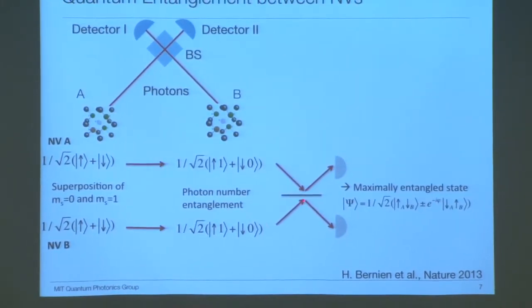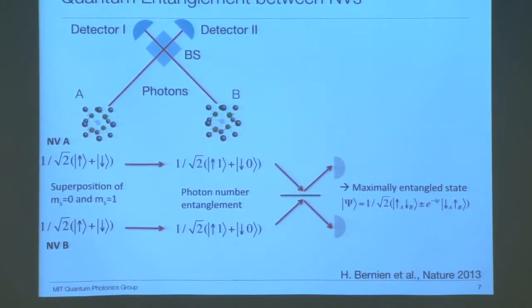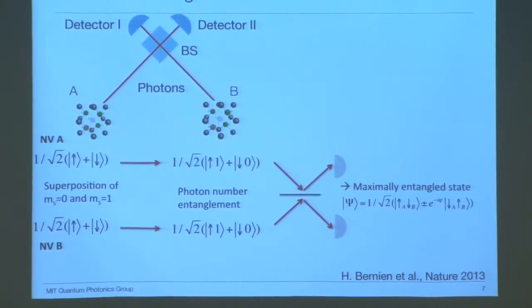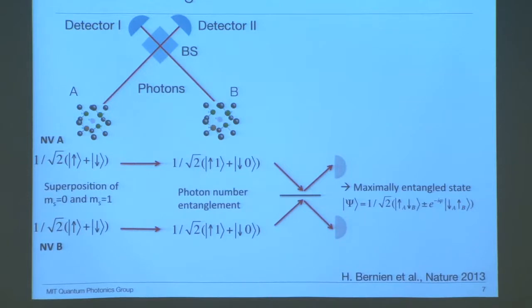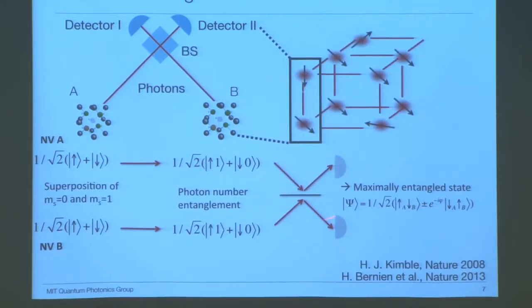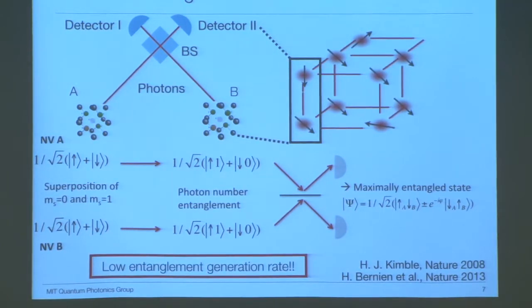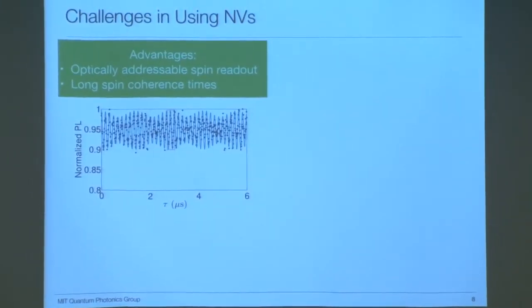These photons are overlapped on the beam splitter and detected at two output ports. Both spins are flipped, and the NV excitation is carried out a second time. The detection of one photon for each excitation cycle heralds the entanglement of two NV electron spins. If we repeat this entanglement operation many times for many NVs, in principle, we are able to entangle a large number of NV qubits and establish a quantum network. But the problem is the entanglement generation rate for this experiment is very low, only one entangled pair per several minutes. That's not good. This brings us to the summary of advantages and disadvantages of NVs.